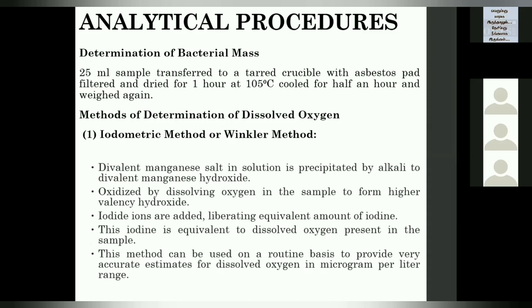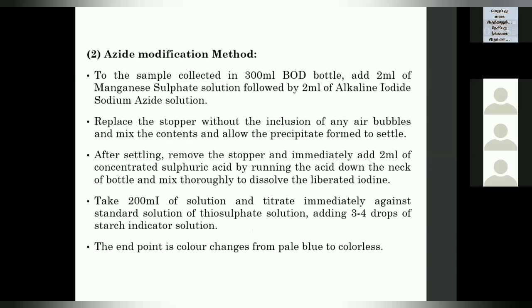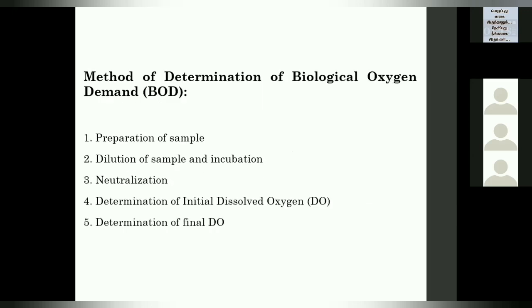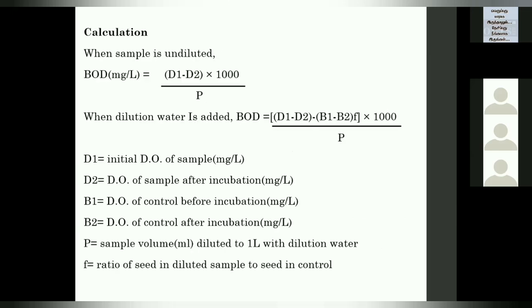Iodometric method was a standard method just for determining the presence of oxidizing agent. Here the oxidizing agent is dissolved oxygen itself, and then azide modification method was used as a standard protocol in order to determine the actual level of DO present. This was a titration method, and color change was from pale blue to colorless, and the starch indicator was used as an indicator. BOD measurement, these are the main steps.